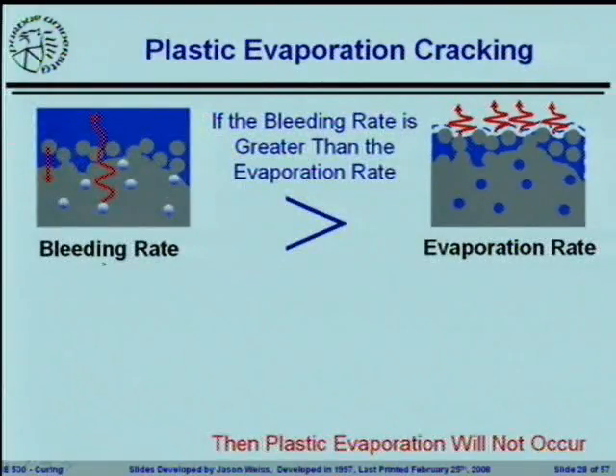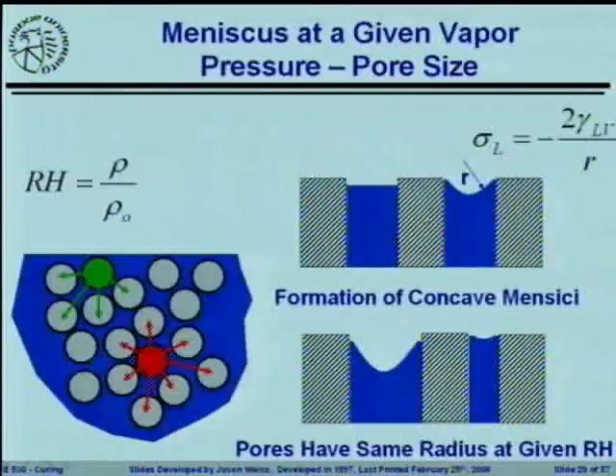If the bleeding rate is greater than the evaporation rate, in general you don't have a big problem. However, if the other is the case, where the evaporation rate is greater, then you can have a problem depending upon when this happens. So if you start getting excessive evaporation taking place from the concrete surface, you can get this potential for the water to start to recede between these two particles. And when the water starts to recede between those particles, you start to build up a tension inside of the fluid. This is an equation that we're going to use quite a bit later on in the semester when we start to talk about shrinkage, volume change inside of the system.